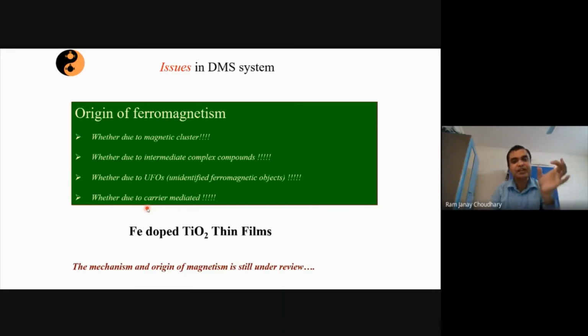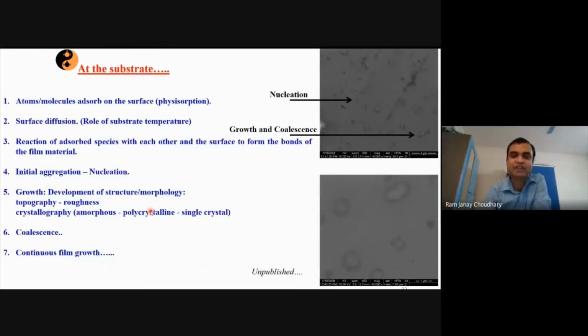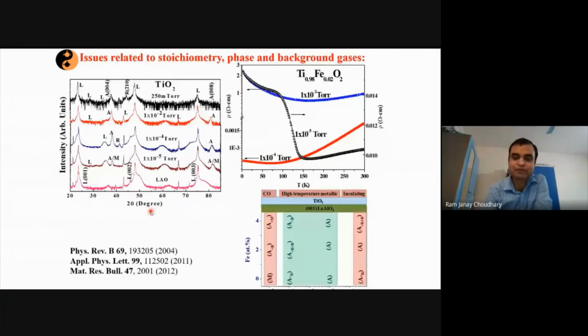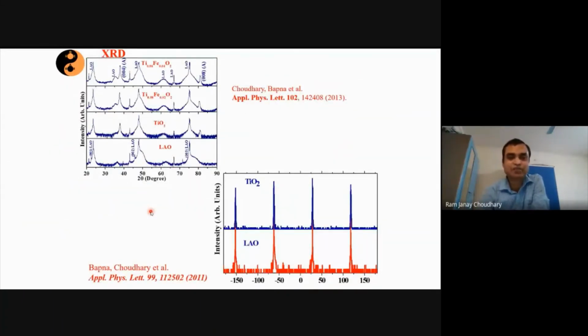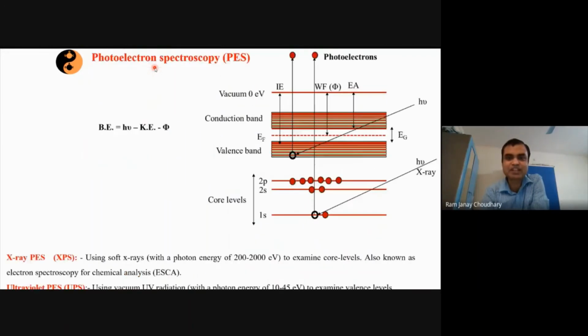See, in case of a metal cluster, you will have metallic bonding between iron, so the effective charge state will be 0. If it is substitutional, your effective charge state will be 2 plus or 3 plus, right? So this is one thing. Another thing is that, suppose because of this dopant it has formed an altogether different composition or different compound, then what you will see eventually is that your structure will differ from TiO2, right? To confirm that, you have to perform X-ray diffraction measurements. That will tell you whether your system is single phase or not. If it was a different material, it will not follow the same structure, right? So these are some of the tricks that one can always use.